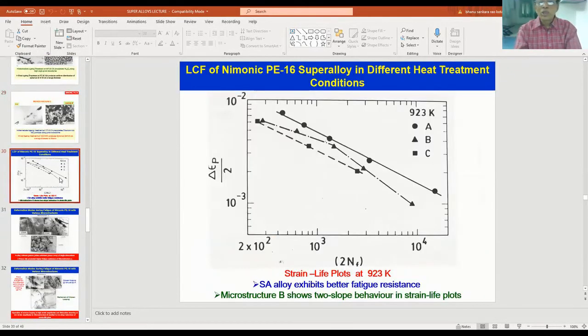You look at that one. This one clearly shows the alloy is the same. Initial chemical composition is the same. Only the heat treatments are different. Here the fatigue resistance is plotted. That is the plastic strain amplitude versus number of reversals to failure under fatigue conditions. These are known as strain life plots, for example, at 650 degrees centigrade, 923 K.